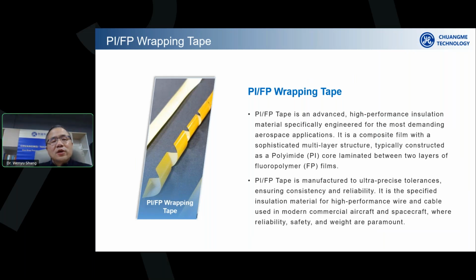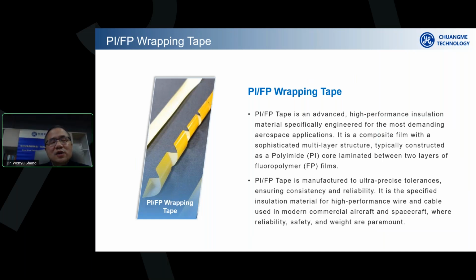Okay, so now, as you can see from the picture on the left-hand side, it's a tape. It's a very thin, narrow tape. When we have this tape, we wrap it at a certain angle, usually between 15 to 20 degrees. We wrap the tape onto the core of the cable with two adjacent cycles of the wrapping overlapping each other. With each cycle overlapping the next, we have an overlapping area with both sides of the PI tape contacting each other.